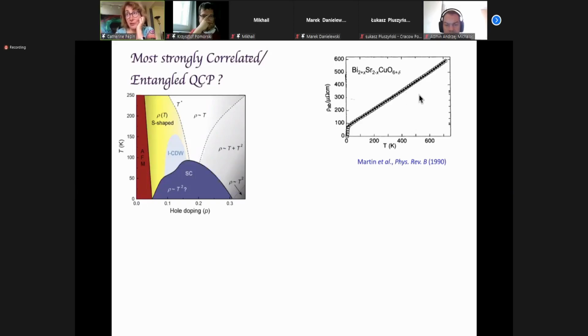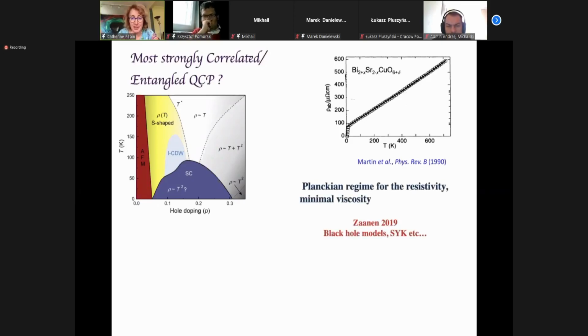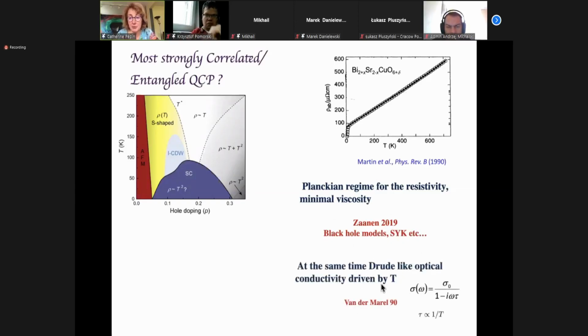Namely, when we started to work on the strange metal phase, we were looking at the papers, and although you have 200,000 papers on cuprates, theoretical papers on the strange metal phase are very few. There are maybe 15. Just to get one theory of the linear resistivity, one transport theory, is notoriously difficult. This is called the Planckian regime for resistivity. Recently there was an analogy with holography where couplings are strong. It has a minimal viscosity. And we know from day one of superconductivity that there is a quasi-Drude-like conductivity, namely the optical conductivity as a function of frequency has a Drude behavior with a time going like 1/T. So the linear-in-T resistivity is also seen in the optical conductivity, within a Drude behavior for which the width is proportional to the temperature. The Drude peak width is proportional to the temperature.